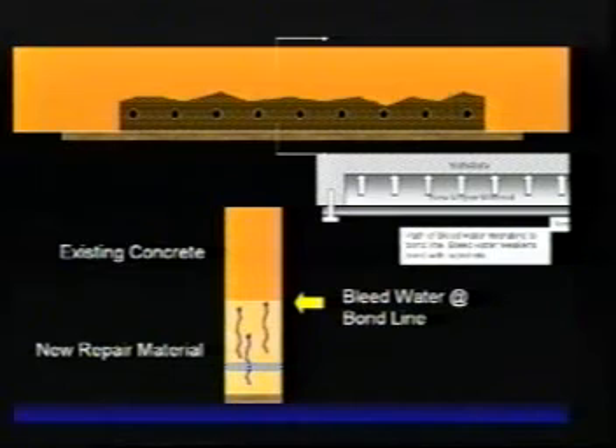The other thing that's very important on work that's done with formwork, especially on overhead form repairs where we're pumping or placing material from the top, is the bleed water issue. The mix design must not allow any bleed water to come up to the surface. Otherwise, that bleed water will accumulate at the interface, right between the new and the old, actually creating a bond breaker.